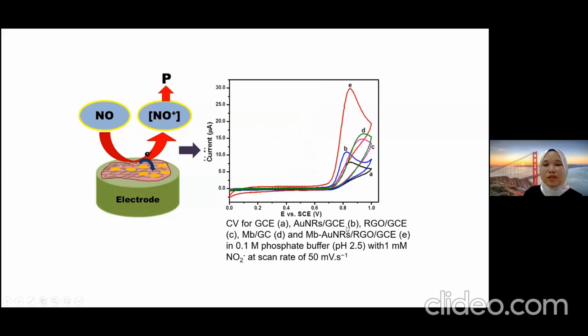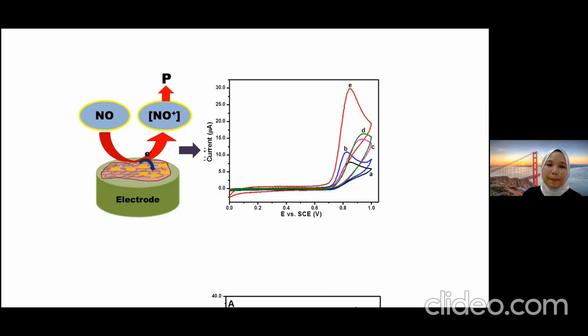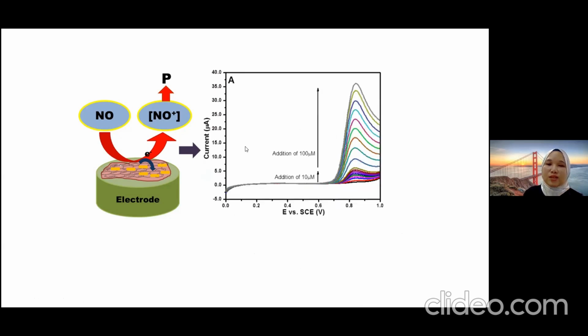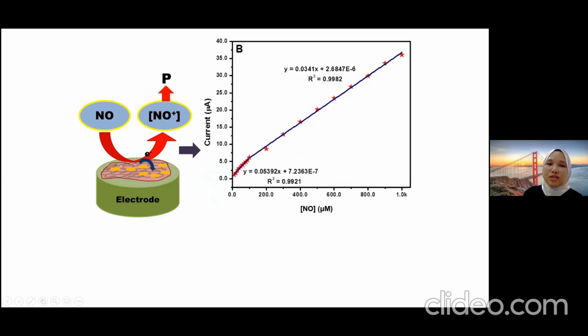So here is a comparison with the other modified electrodes, such as gold nanorod only, reduced graphene oxide only, and also myoglobin only. As we compare with those modified electrodes, the nanohybrid shows the highest peak current. In addition, we use the LSV with additions of sodium nitrite from 10 micromolar up to 100 micromolar. And from this regression graph, we can calculate the limit of detection to be 5.5 micromolar.